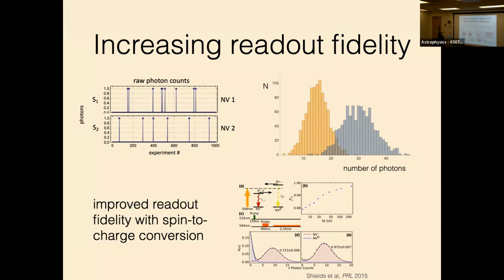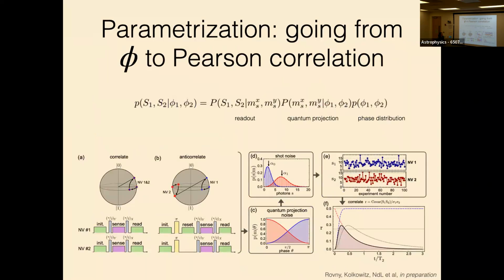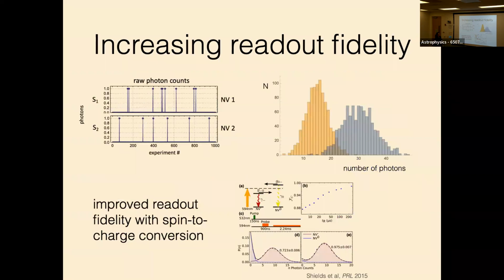So the key thing, from this perspective, is that I need to be able to cleanly separate these distributions and decrease this readout noise in order to get any shot at measuring correlations. With the traditional spin readout, this is very, very difficult to do. But one of the things that I worked on right before leaving Nisha's group, together with Brendan Shields, was this mechanism for improving your readout fidelity using spin to charge conversion. It turns out that there are ways to selectively ionize the NV center to convert the spin state into a charge state. And then it's very easy to read out the charge state with single shot fidelity.